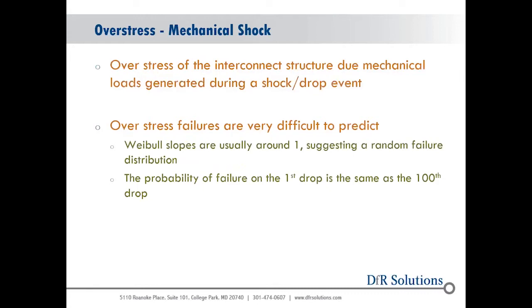When we're talking about overstress, yes, you can break the component package, but really it's going to be the interconnect structure. This could be pretty much what's on either side of the solder joint itself. They're very difficult to predict an overstress failure because it really is a high strain rate type of event, crack propagation through a very brittle material for the most part. And typically we see it as a random failure distribution. So if we're at overstress type of levels, the probability of failure on the first drop would be the same as the 100th drop, so a random sort of failure distribution.